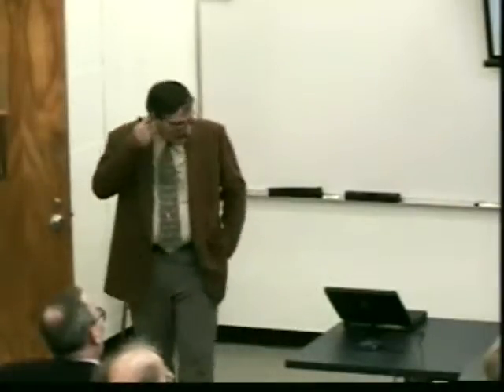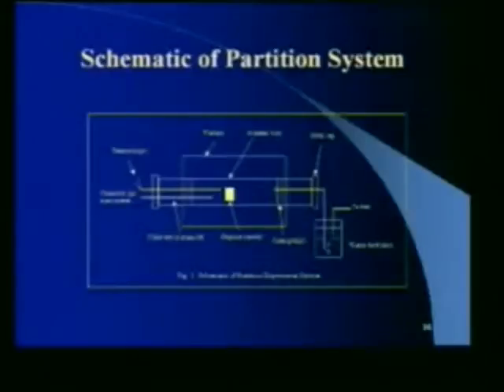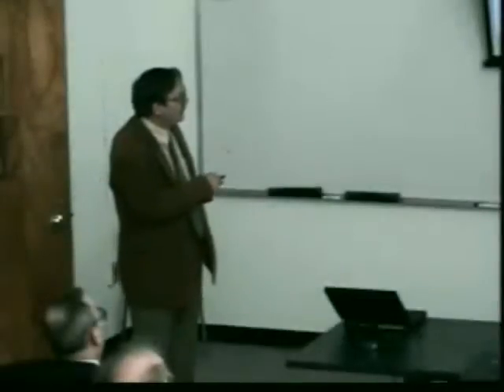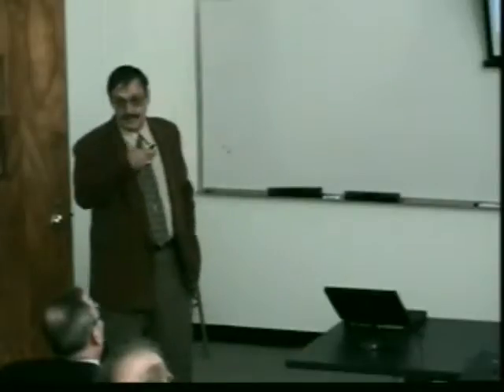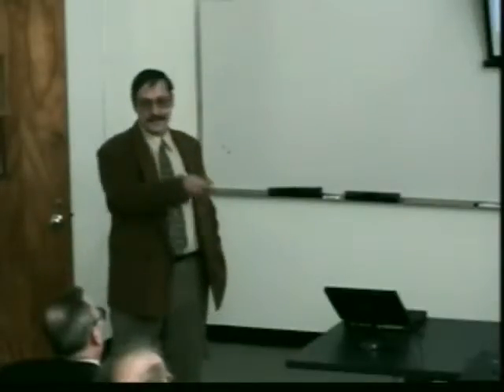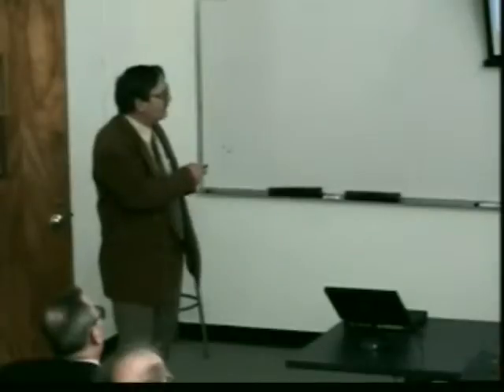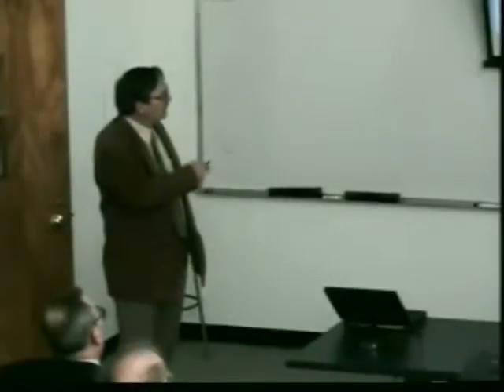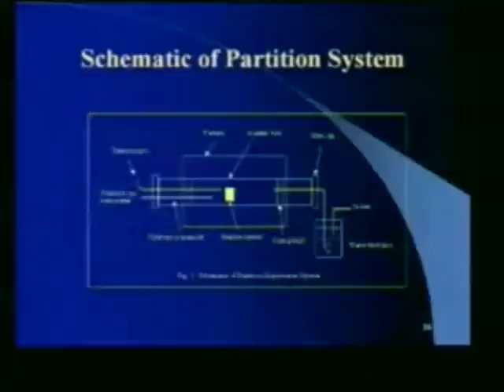This is not going to show up real well either, but this is the schematic showing the reactor system for these volatility studies. What we have is a crucible here, in this particular case graphite. You heat this furnace up to whatever temperature with the glass phase and the material that you want to see if it stays there or goes into the vapor phase. You leave it there for a period of time. There's a thermocouple for temperature. There's gas that flows through here. It carries any vapors over to a water condensation bath where you collect them.